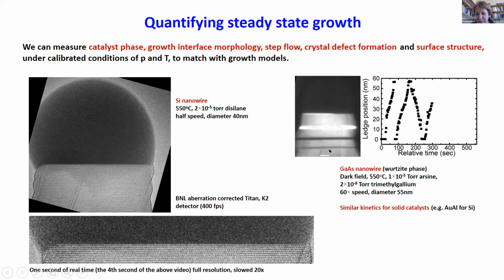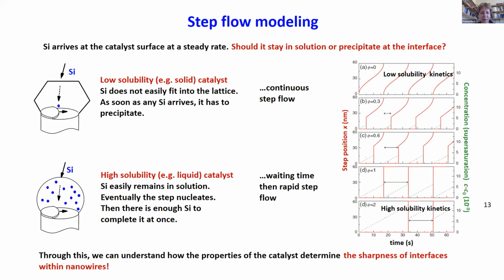We can also go to other materials. How about gallium arsenide? So we flow trimethyl gallium and arsine with gold catalysts, and we get very different results. Look at the growth of these things. Do you see how the step is moving slowly at the interface, back and forth across the interface? And this very different growth kinetics can be used to derive some of the physics of what's going on.